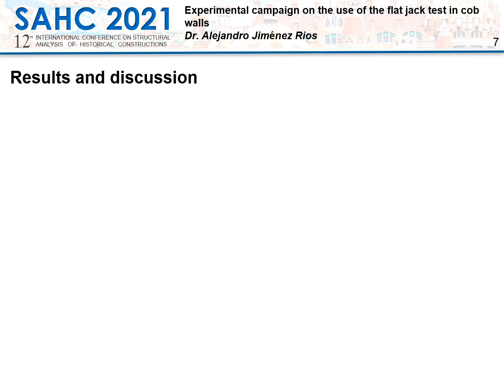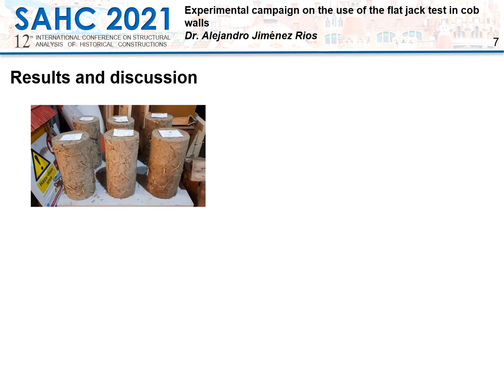Six cob cylinders were prepared using random samples of cob mix prepared for the construction of the wallets. The cylinders had dimensions of 15 centimeters diameter and 30 centimeters length. They were left in the lab during a drying period of 3 months, during which their size and weight were controlled to estimate shrinkage and density.